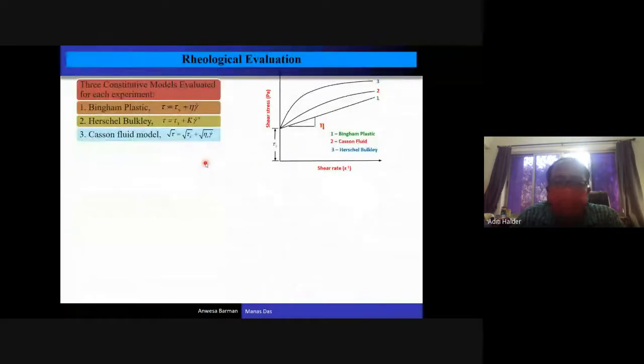Now this MR fluid has rheological properties, because if you consider a Newtonian fluid, in the shear stress and shear rate plot there will be a straight line starting from the origin of this curve. For a non-Newtonian fluid like MR fluid, there is a yield stress and a plastic viscosity. This means it does not start from the origin. When the applied pressure is greater than the yield stress of this fluid, only then will this fluid flow. After flowing, the slope of this curve is called the plastic viscosity.